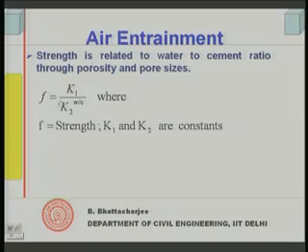And similar to Abrams' law, other laws exist, like Feret's law and the gel space ratio relationship, but Abrams' law seems to be most acceptable in many mix design procedures, with some variation of this form in graphical form, etcetera. So, that is why I am repeating this. This seems to be very valid even in the case of concrete, like the cement paste we mentioned. As water cement ratio increases, strength reduces. K1 and K2 are constants depending upon the type of aggregate, type of cement, everything. All other things remaining constant, strength of concrete is inversely proportional, in terms of a power, to the water cement ratio. That is the most important idea.